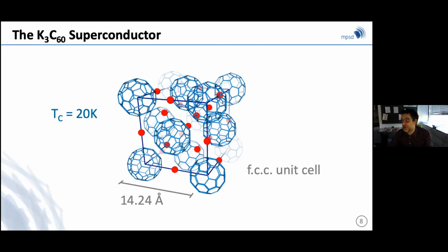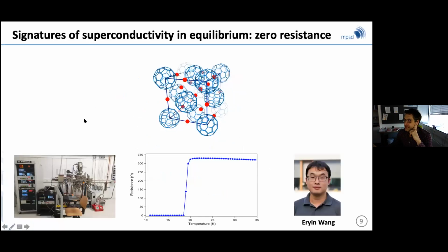So, alkali-doped fullerenes. The way we should think about alkali-doped fullerenes, in its most romantic and stripped down view, is that of an FCC lattice of C60 molecules, which are electron doped 3 times by 3 alkali atoms. Basically, think about an FCC lattice of C60^3- molecules in which the lowest unoccupied molecular orbital is now being filled by 3 electrons. And this material becomes superconducting in the potassium case at approximately 19 Kelvin.